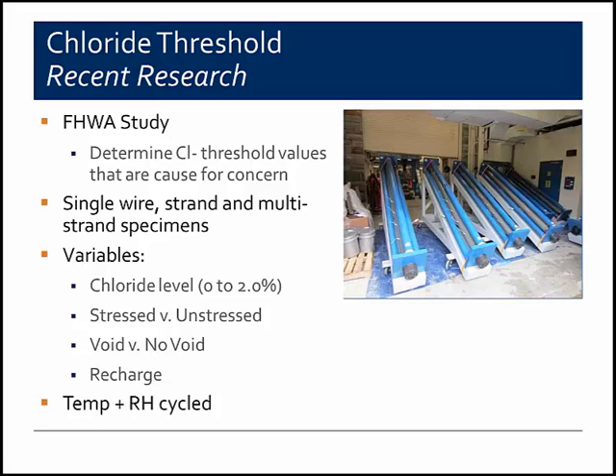The variables they looked at were also chloride level. Unlike Sika, they evaluated stressed versus unstressed conditions, again, to try and more accurately model an actual tendon. And there is some research that suggests that stressed strand will have a lower corrosion threshold than unstressed strand. They also modeled voided specimens versus unvoided, and they evaluated the effects of recharge with certain voided specimens where water was introduced into the sample. And unlike Sika, Federal Highway is cycling the temperature and relative humidity conditions to more accurately model seasonal changes.